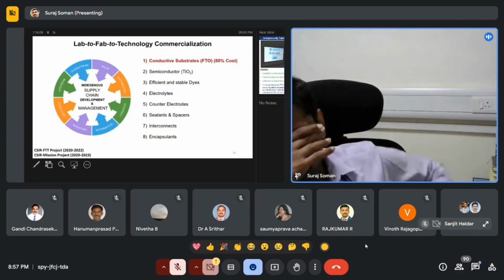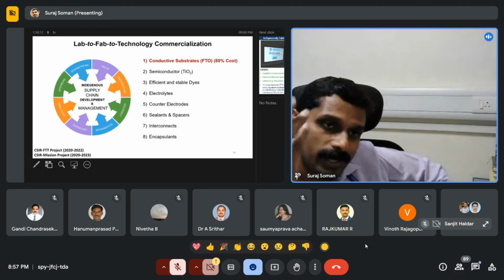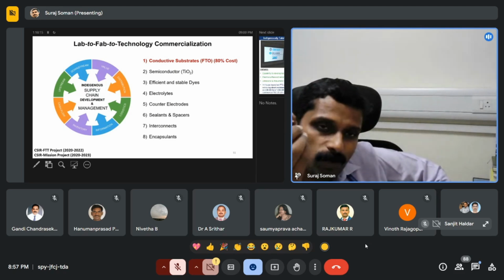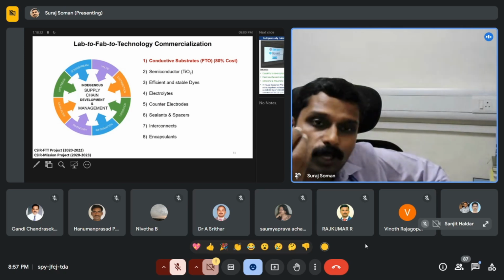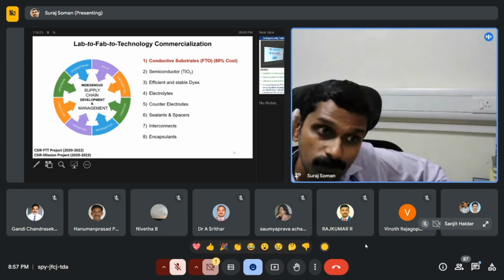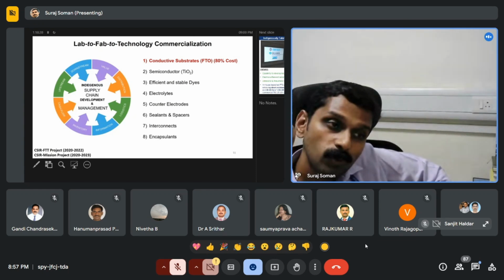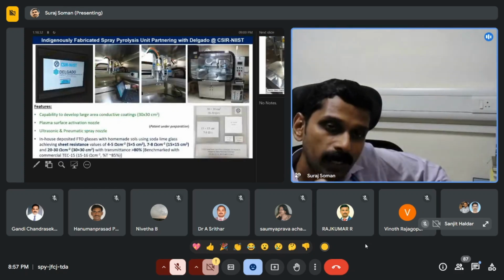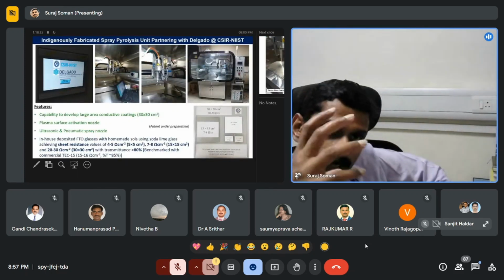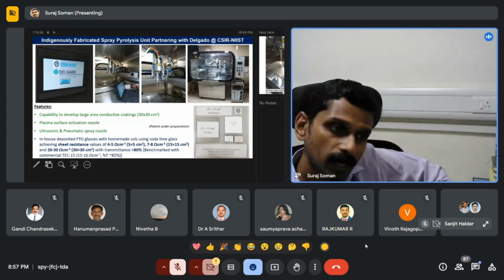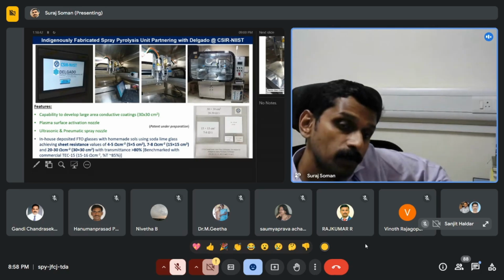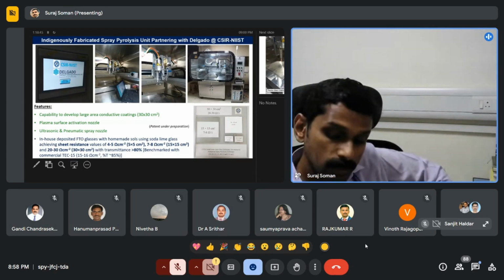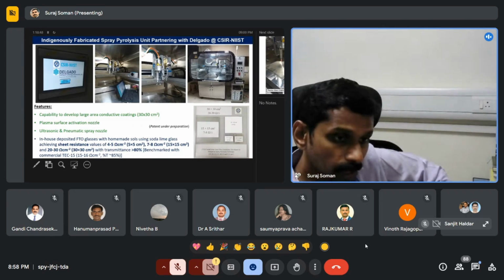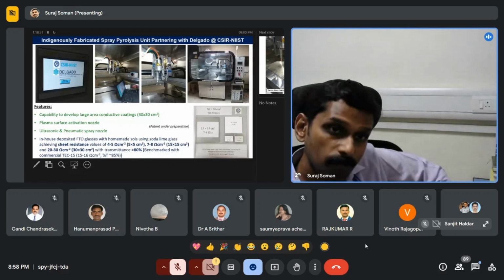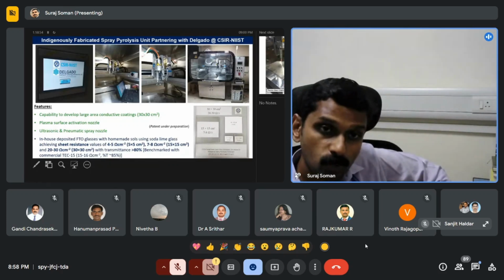Then the point comes, when it comes to this solar cell, it is not just the dye, the semiconductor or the electrolyte, but one of the major things that contributes to the cost is the conductive substrate, the FTO substrate. That occupies almost 80% of the cost. So if you really want to commercialize, you need to indigenize that coating. This is where we partnered with a startup company and designed a set of spray pyrolysis based equipment, and we optimized the process, where presently we make conductive oxide coatings with sheet resistance better than even the commercial conductive glass coated substrates that you are getting.